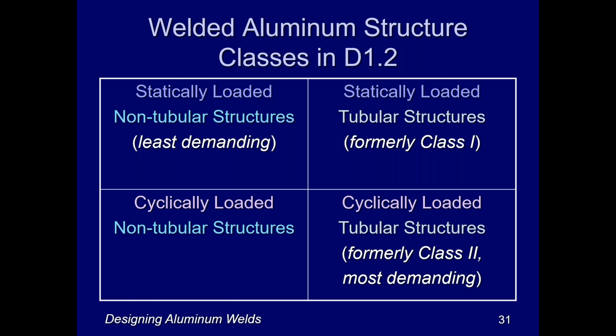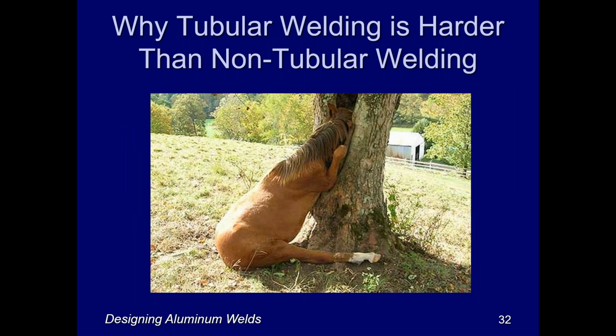Now, it might be obvious that static loads are a little easier and less likely to crack your weld than cyclically loaded situations, but what's up with the tubular stuff? I mean, how does the weld know whether you're welding a tube or a plate? Well, this picture was not originally intended to illustrate the difference, but as soon as I saw it, I realized that it does a great job of doing that. And the reason that tubular welding is more difficult is it's very difficult to see the backside of a weld on a tubular part. To inspect the weld back there, or to put a backer bar back there, or to back gouge back there and weld from the other side is almost impossible because you don't have the access. And so tubular welding is much more difficult than non-tubular. And in extrusions, we tend to think of hollows as opposed to solid shapes, but you get the idea.